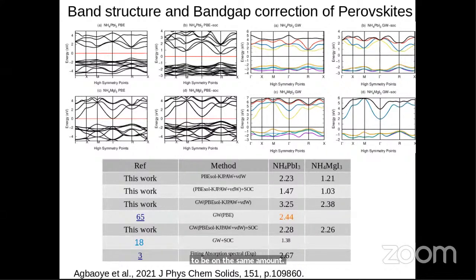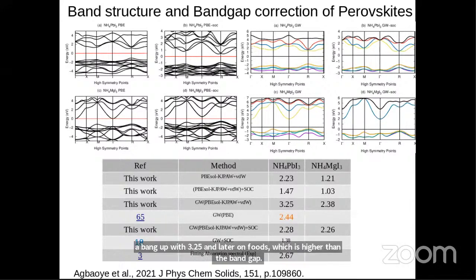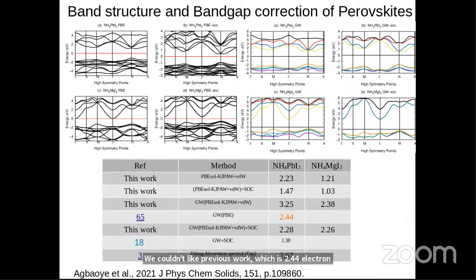achieve a band gap of 3.25 electron volts, which is higher than the band gap recorded by previous work, which is 2.44 electron volts. But at the end of the day, when we did the GW calculation with the PBE functional, with spin-orbit coupling, we are able to achieve a band gap of 2.28 electron volts, which is closer to the experimental work done by previous researchers, getting a band gap of 2.67 electron volts. So here we did not achieve the exact experimental gap, but we have a better gap compared to what DFT is offering.